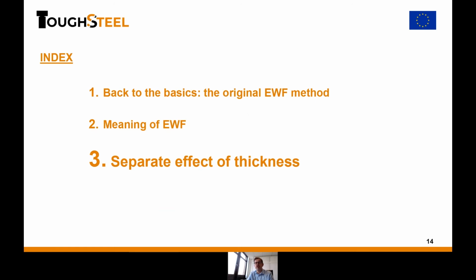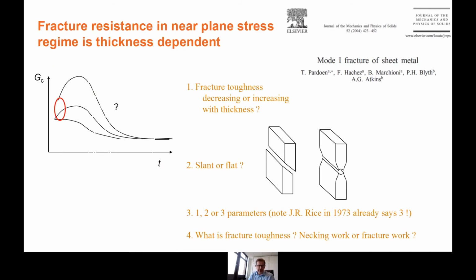That was about the meaning of the essential work of fracture and also this question of necking and fracture. Now I want to go deeper into the fact that the essential work of fracture, and as a matter of fact J1C would be the same, is a combination of two contributions. And this is the core for understanding this not so well understood evolution of fracture toughness. Here I call it GC, but it could be essential work of fracture, or JC, J1C. This is the evolution of fracture toughness with thickness.